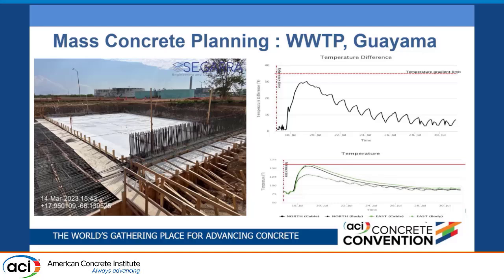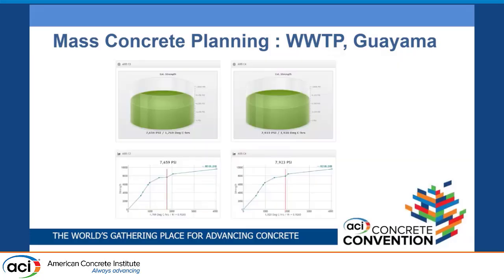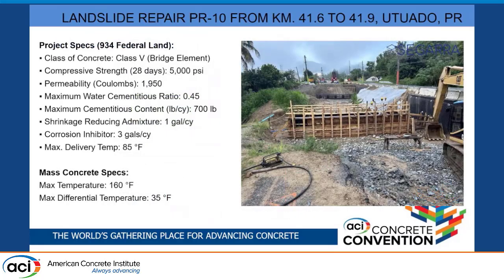What's going to be the curing method for those mass concrete? In this case, we used white blankets, wet blankets, and foggers all around the structure for all the foundations. And if you can see here on the charts, we were under the gradient limits between the centroid and the surface, and also the limits of the maximum temperatures, using slag cement and very low cement content. And we achieved the maturity testing with our mixes.